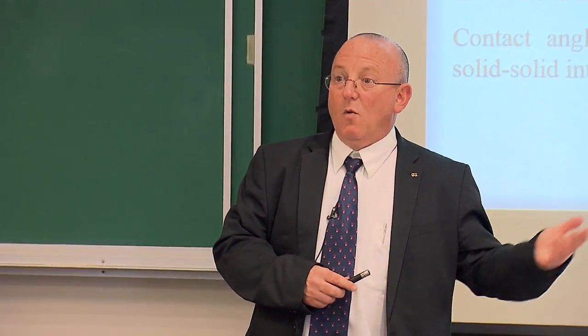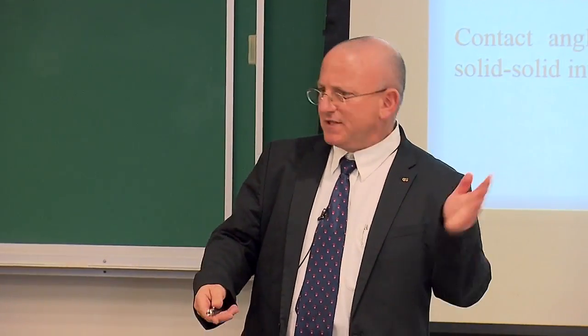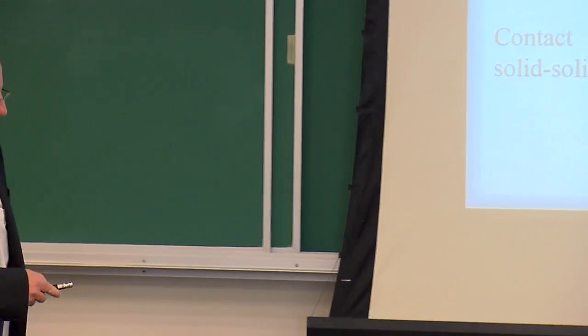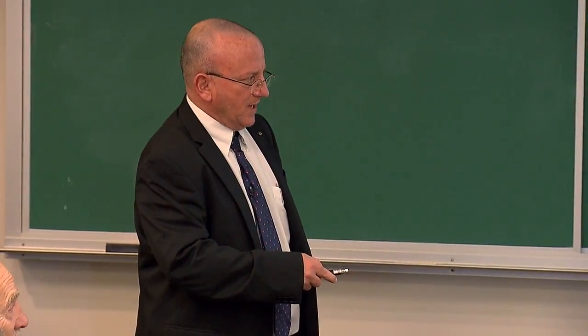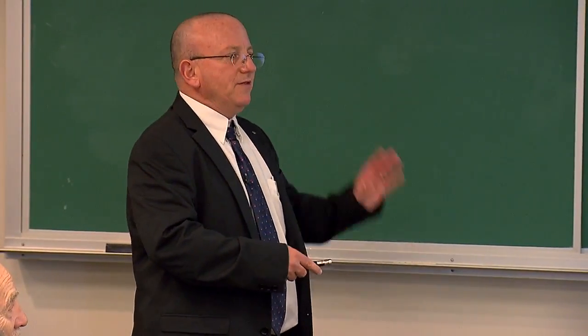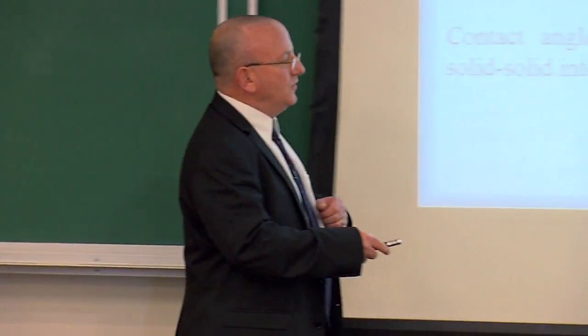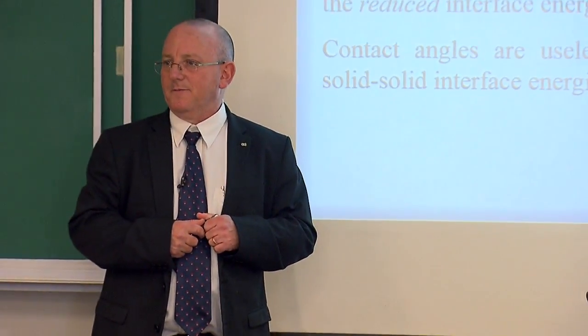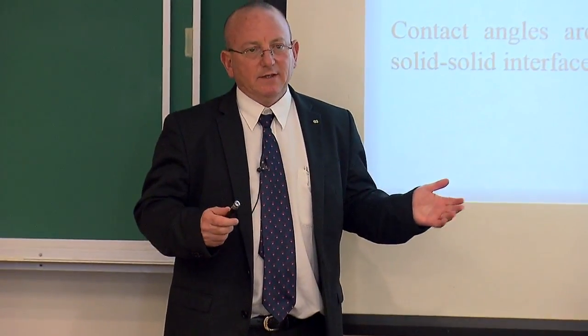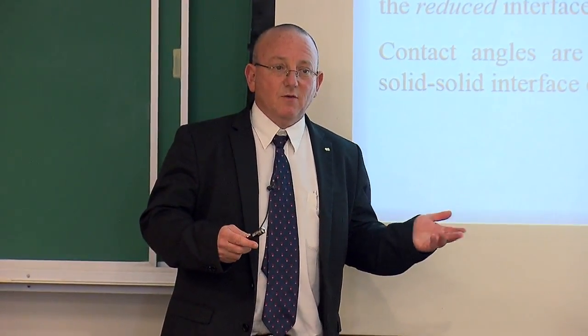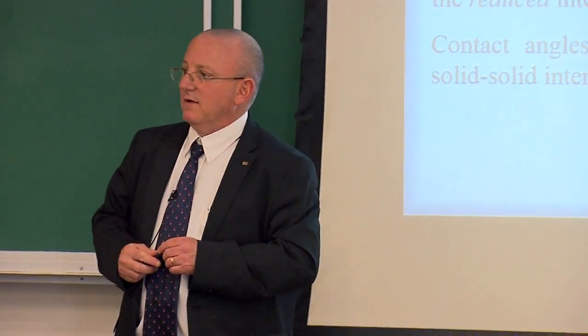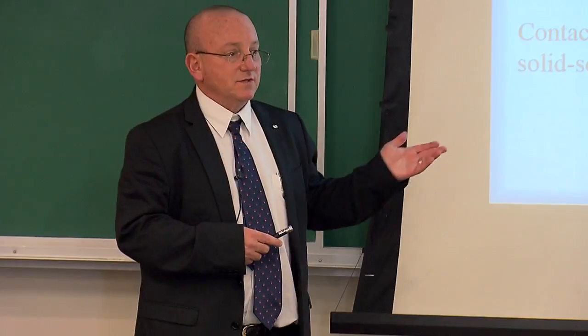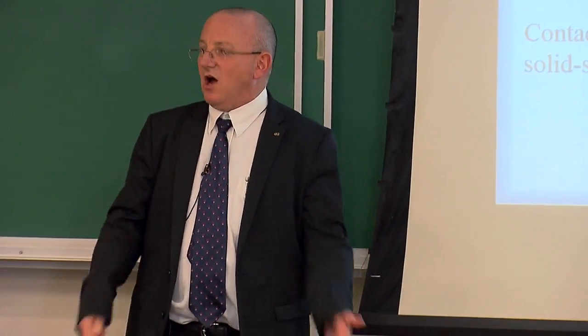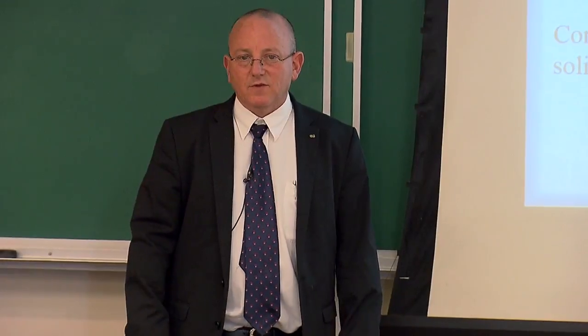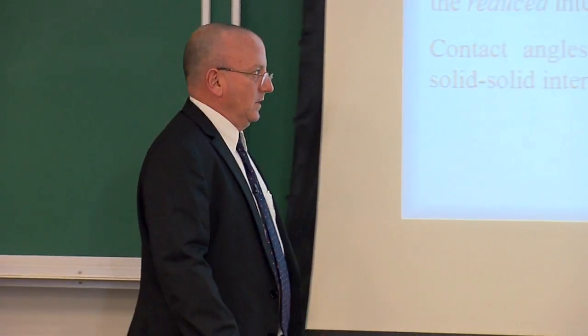And therefore, the system wants to increase the area of the interface at the expense of the free surfaces, right? So now we have a much larger area of contact than we did before. The only thing I've done in this thought experiment is reduce the interface energy itself. That's it. But you will notice immediately that the equilibrium crystal shape of the solid hasn't changed. We've just truncated it at a different point. And therefore, the contact angle also doesn't change. So you can't use contact angles for solids like you can with liquids. Very simple proof, which can be done much more elegantly mathematically.